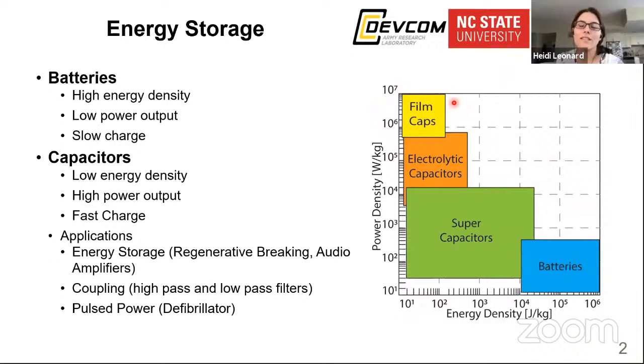So can you speak to the reliability of your samples? Yeah, so when we talk about reliability, we think of how many times you can cycle this sample before it breaks. We've done some characterization on that front, and we can cycle our capacitors up to 10 to the 7th times at 40% of the breakdown field with no change in behavior. We've also done a study where we land on electrode 1 and do all the measurements, land on electrode 2, do all the measurements, and start comparing where and when our samples break down, from sample A to sample B to sample C. We have shown with a Weibull distribution that we have really reliable samples overall. It's not just that we got the magic sample for these numbers. If you test a lot of our samples, you still get these results. So they're very reliable. It's impressive.